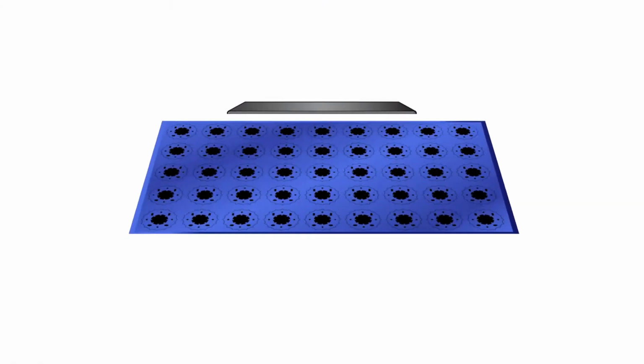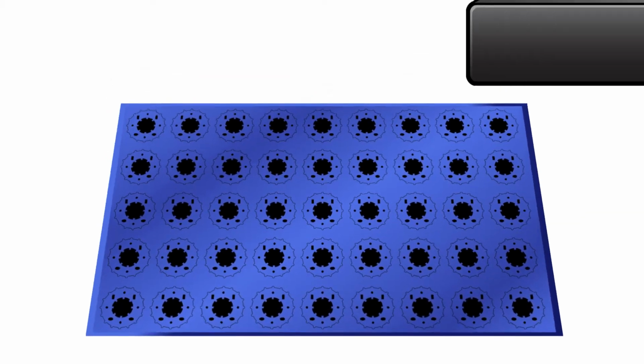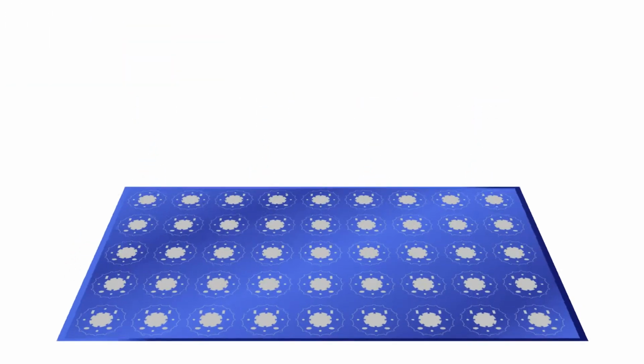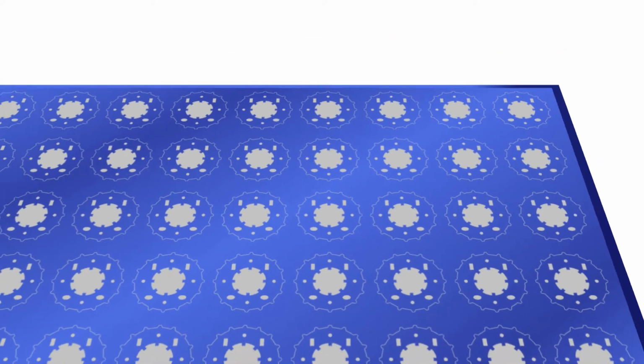In a vacuum frame, the resist-coated metal is sandwiched between the top and bottom layers of the photo tool and then exposed to intense UV light, which hardens the resist in the pattern of the parts. Unexposed resist is washed away in developing solution in an automated machine, leaving bare metal in the areas to be